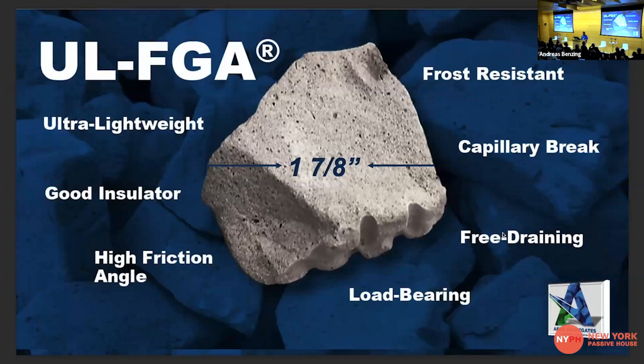So foam glass aggregate is ultra lightweight. The unit weight of the material is 15 pounds a cubic foot. That's on average 85% lighter than natural aggregates. It's a very good insulator, has an R value of 1.7 per inch. It has a high friction angle, which means it interlocks together very, very well. It's frost resistant. It serves as a capillary break, and it's free draining. One of the keys to this material is it can be in contact with water and it's not going to degrade.